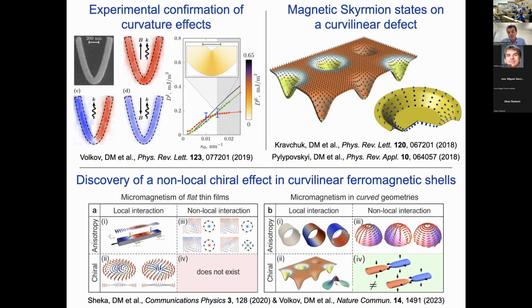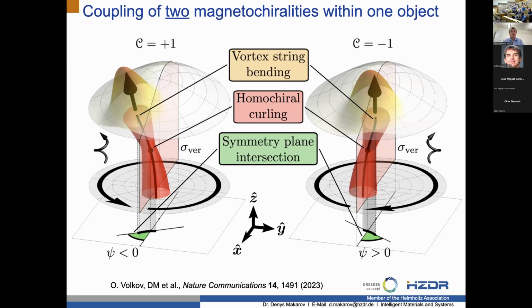There were a couple of years of very intense collaboration between the groups to understand what is the physical consequence of such non-local chiral symmetry breaking. And now, this year, we have a very interesting achievement, which will be discussed by Alexei Volkov in his talk: that even in such standard, very classical objects like the magnetic vortex state, where you have a circulation of magnetization in a magnetic nanodot, you can induce two magnetochiral properties, one being the chiral properties of the magnetic vortex texture, and also the change of the twist of the magnetic vortex string. This is quite an interesting physical observation, but we were still lacking it because such structures did not exist before.